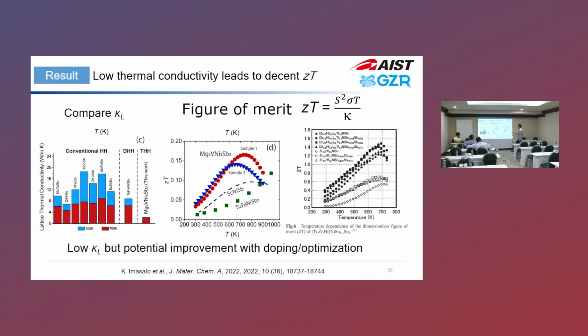But also, if you compare to other double Half-Heuslers or scandium nickel antimony, it's also higher. And if you take a look at the example of conventional ternaries, this is just one single phase. It didn't have alloying or dopant, and they just slightly changed the composition to tune the carrier concentration. ZT can be much higher, like 5 times higher. So we can think of this as a parent composition again, and if you tune the composition a little bit more, there is a potential to have a much higher thermoelectric performance, I guess.